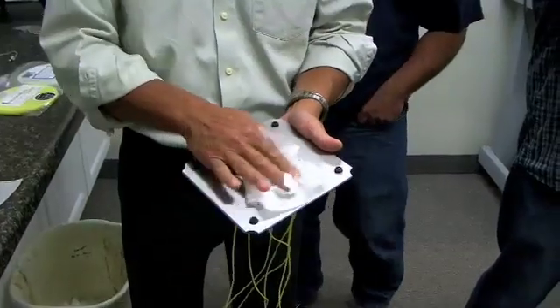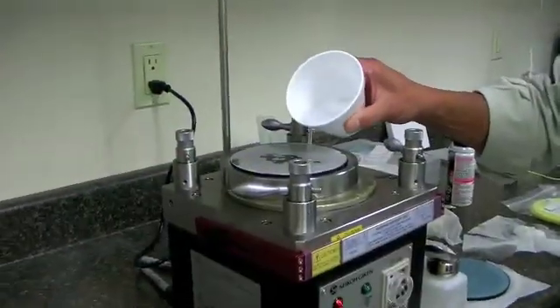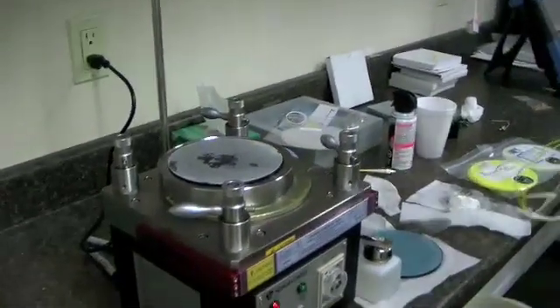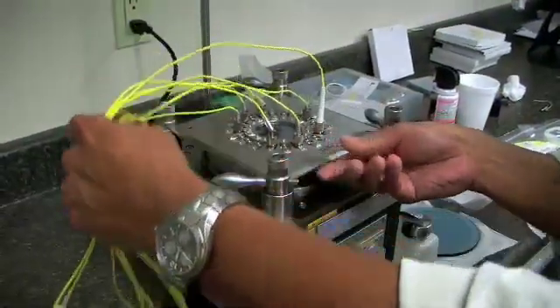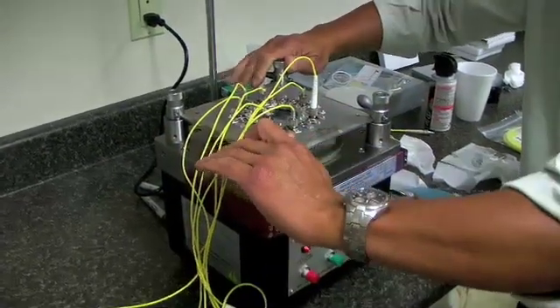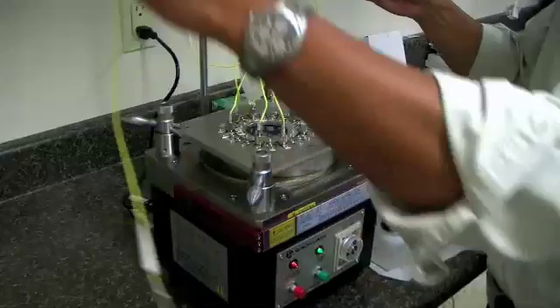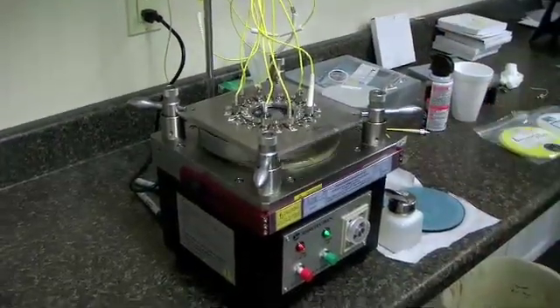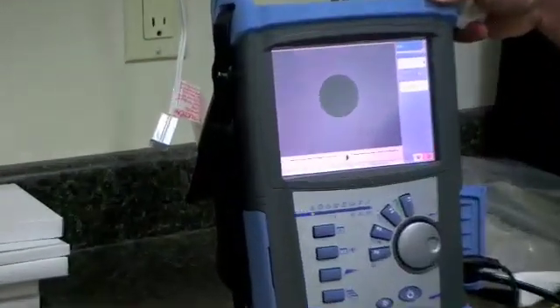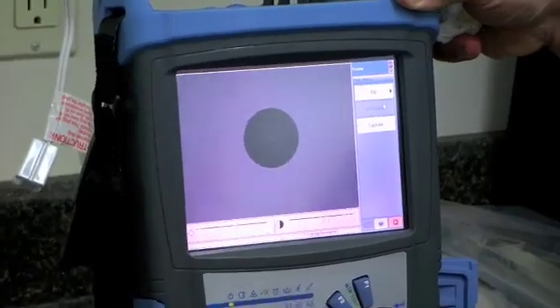After the third polishing, we re-clean the plate and begin the fourth polishing. I took that one off because there's no fiber. I'm going to do it 30 seconds. That's a good polish connector. No defects in the core. Core cladding. Zero defects. Cladding, you can accept a certain amount of things in it. Just a little bit more pits and scratches, dust and light scratches.